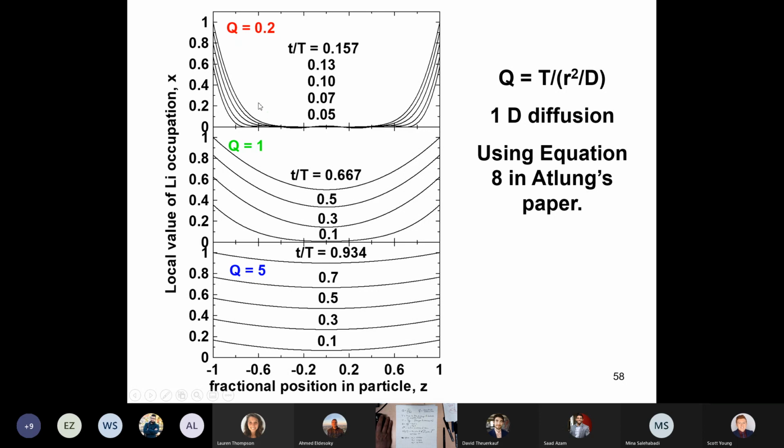Okay. And if you look closely at this graph, you'll see there's some little oscillations in it. This is because in this calculation, I only use the first 3 values of alpha in the summation in the formula. People in my group that have been associated with diffusion studies know that to eliminate these oscillations, you need to include quite a few terms in the expression for X, big X. But for the purposes of our class, we'll only include the first 3 terms just because it gets too cumbersome to put in more. Okay, so any questions about this graph?